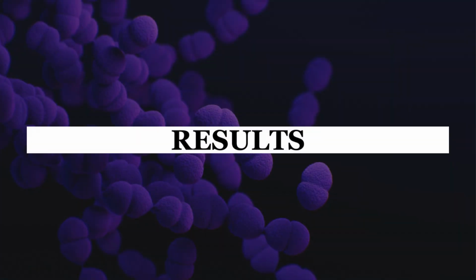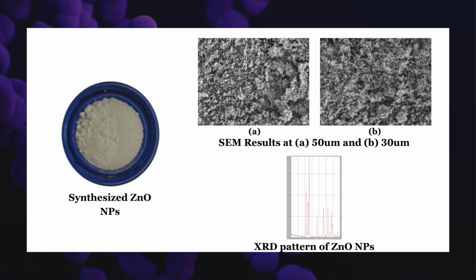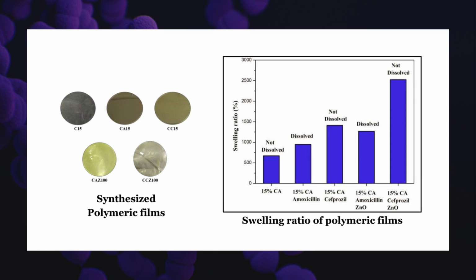Results. The analysis of ZnO nanoparticles synthesized in this study revealed that the ZnO nanoparticles exhibited hexagonal crystalline structure, spherical shape, and a size in range of 100 to 200 nanometers. The most optimal concentration of cross-linking agent, citric acid, was found to be 15%. The swelling ratio analysis of the synthesized polymeric films revealed that the films exhibited a very good swelling ratio, thereby making them a suitable material for wound-healing bandages that could absorb the wound exudates.